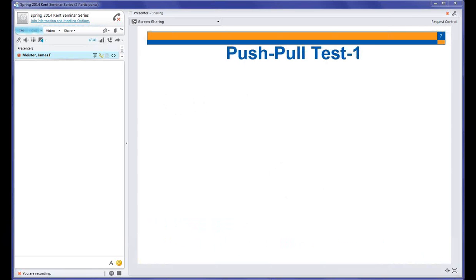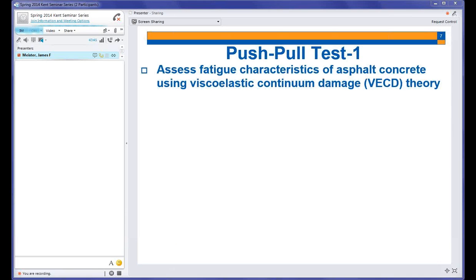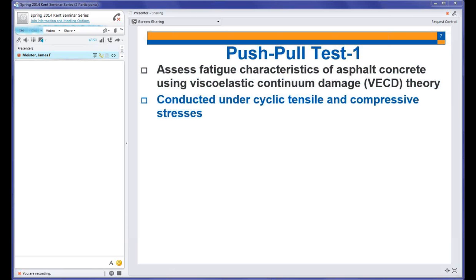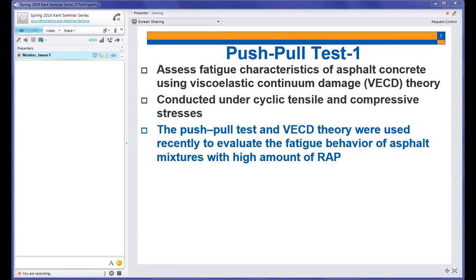The second test is the push-pull test, which is a relatively new test in our lab. This test uses the viscoelastic continuum damage theory in order to assess the fatigue properties of the asphalt mixture. It applies cyclic loading, tension, compression until failure. It was recently used before my study to evaluate the fatigue properties and fatigue performance or behavior for mixes with RAP. Actually, Dr. Kazi, who was a student here, used this for mixes with 50%, 40%, and 30% RAP.